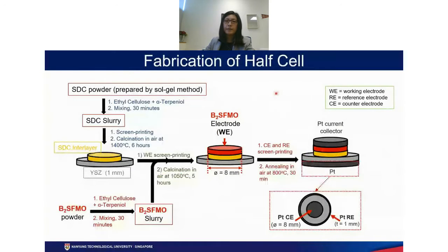So we go ahead and make our half cell for evaluation of the electrode. We have an SDC as an interlayer. We use YSZ as the electrolyte and put an SDC interlayer, and then we go through all the process to put the electrode. We use screen printing to put our B2SFMO electrode on it, and then we also put the calcinated.